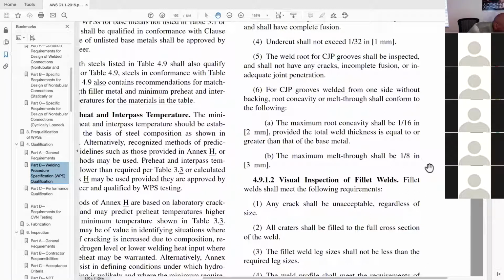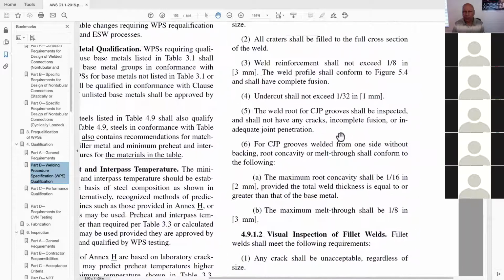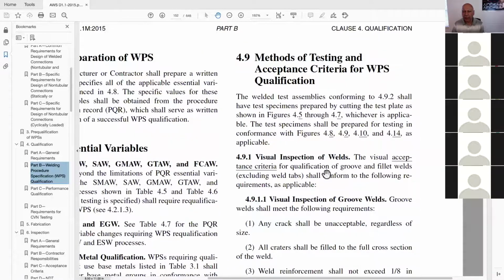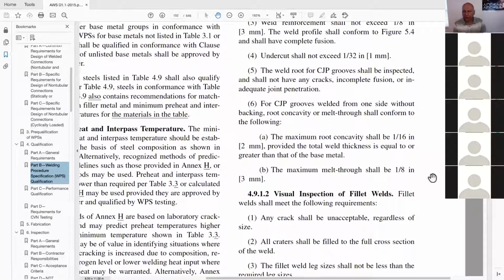does this apply to pipe and tube only? No, remember, this is a WPS qualification. So can we actually qualify a procedure without a backing and without back gouging or back weld? Yes, we can. That's why it's just simply not pre-qualified, but nowhere in this code book does it say that it was prohibited. So we can actually qualify a welding procedure with an open root without back gouging and back welding, as long as it is qualified by testing. So this would apply for pipe also, but for plate as well. If we were trying to qualify this procedure without a backing and without having to back gouge and back weld, then we have to consider A and B and number 6.